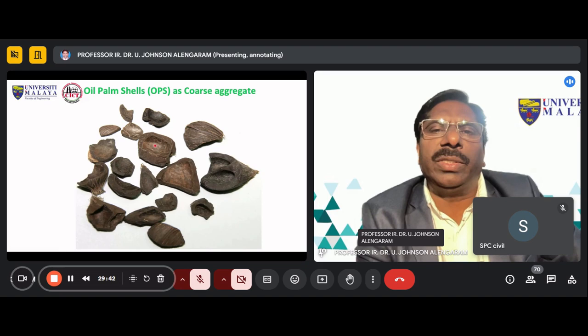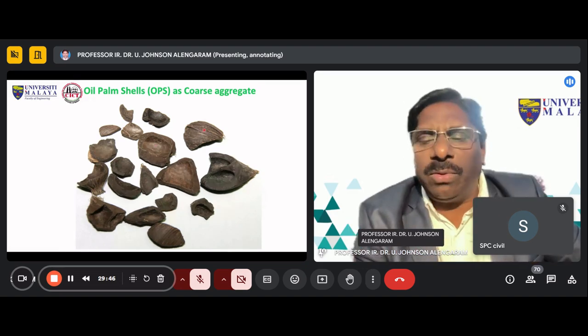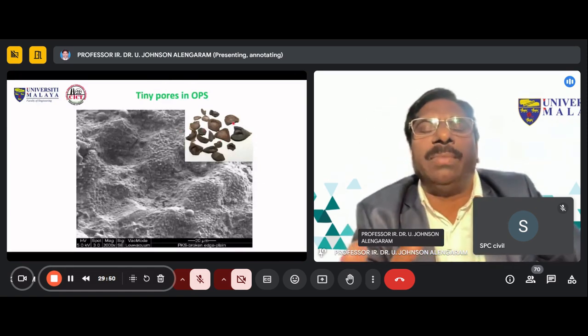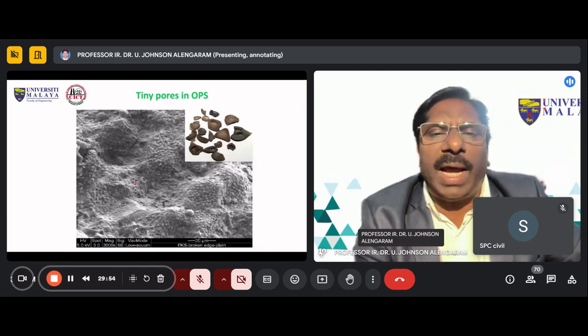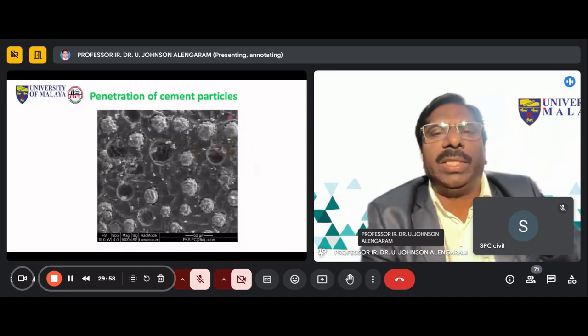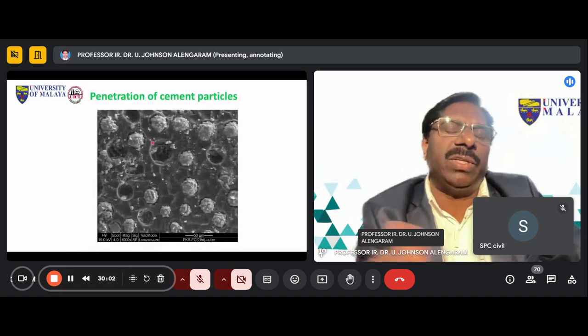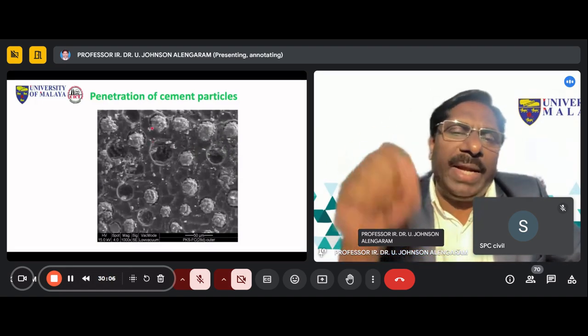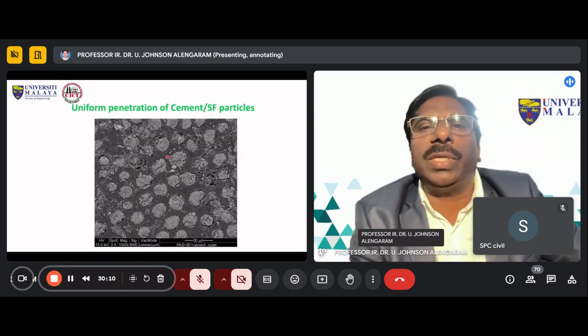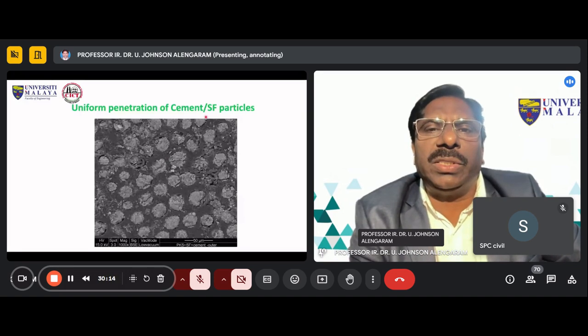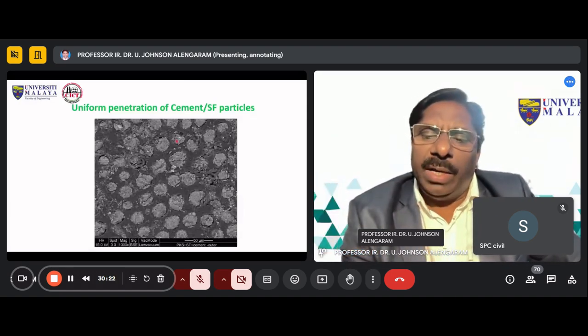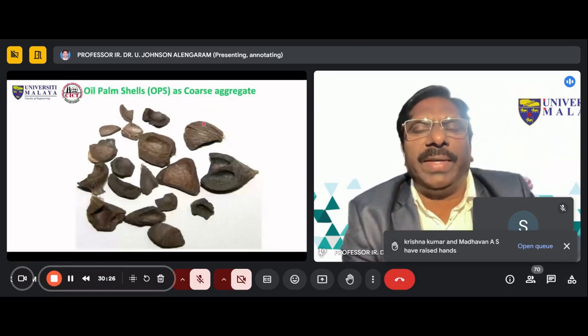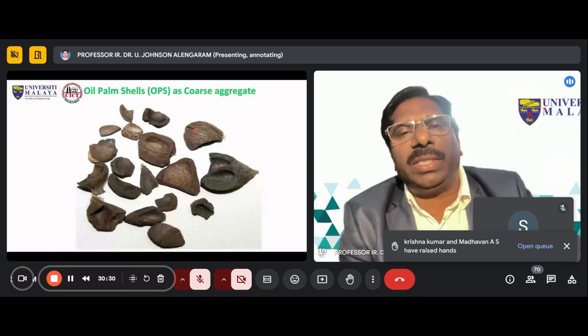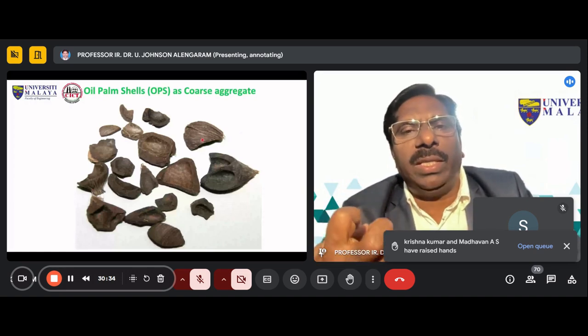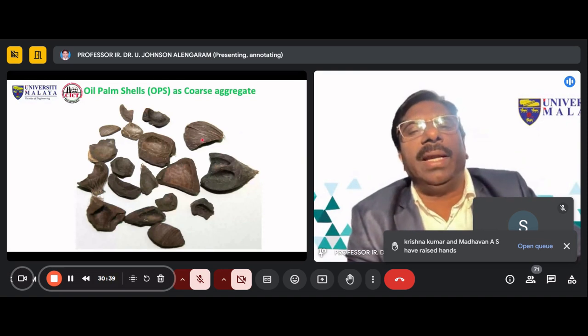For instance, the bond between this convex surface and the cementing matrix will not be that good. Therefore, we have to use silica fume, which is 100 times finer than the cement. The tiny pores on the surface have to be filled, which is not possible with cement particles. Cement particles with an average size of 40 or 60 microns cannot penetrate these micropores. So what do we do? We have to use silica fume. When we use silica fume, these 7-micron size pores are impregnated with the silica fume particles. Thereby, the bond between this surface and the surrounding matrix improves. When you have a bond, then the transfer of force between the matrix and the aggregate will be good, and thereby it can lead to ductility.